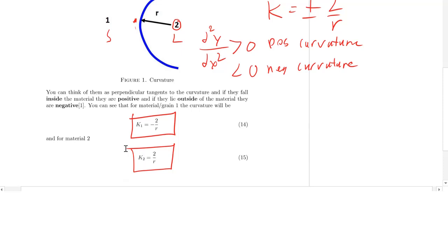Because if you remember back, we had this expression for the chemical potential of a sphere as that of an infinite plate plus or minus 2 times your surface tension times V bar over R. Notice here we have basically curvature.